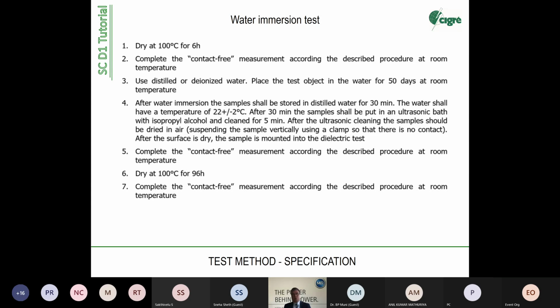It's water immersion because, as I mentioned before, the microscopic interfaces in composite insulating materials are mainly affected by moisture. So we can trigger potential aging mechanisms with moisture. So we can stress the material in an easy way. And most probably, this is also the dominating aging effect that we see in real application in the field. So we defined a procedure.